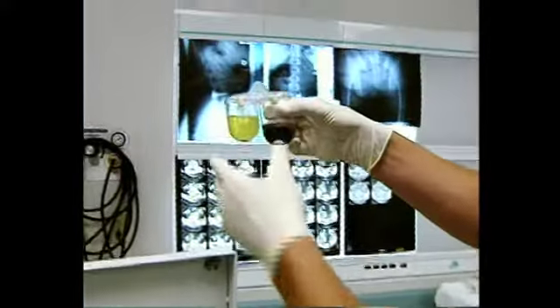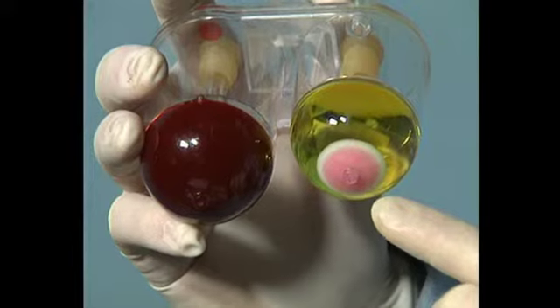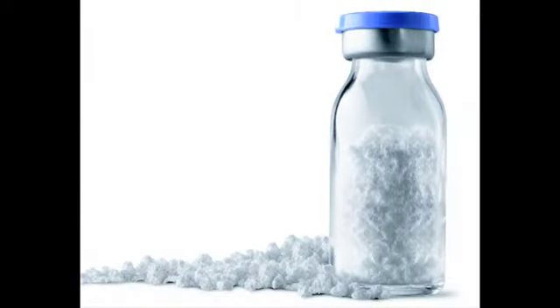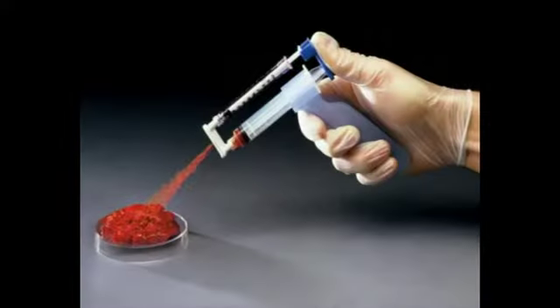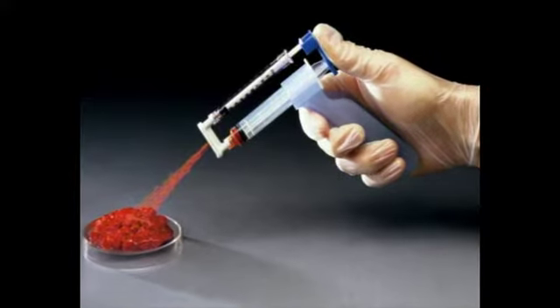Radiographs revealed no evidence of instability within the acetabular component bone interface and no evidence of bone graft migration into the pelvis. Radiographs taken at 2 months revealed increased bone formation across the inner table with reduced lucency about the acetabular shell. At 3 months, radiographs continued to show increased bone formation across the inner table without evidence of instability. Augmentation with platelet-rich plasma enhances bone graft containment and handling characteristics. Results from this case suggest that Conduit TCP granules augmented with platelet-rich plasma may be an effective way to handle severe acetabular deficiency in revision total hip arthroplasty.